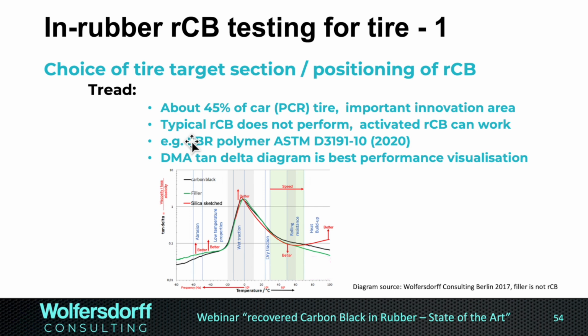This is really, really rarely used for RCB. In fact, I made this diagram because I wanted to compare the carbon black, which was an N660, with a filler which wasn't recovered carbon black. And the silica I only sketched, I didn't have data, but of course the silica in the dynamic mechanical analysis is much better than the 600 grade carbon black, and much, much better than the filler. I won't go into the details because typically for RCB this is the dream, but at the moment we cannot live the dream yet if the reinforcement properties are not even close to an N300 group carbon black.